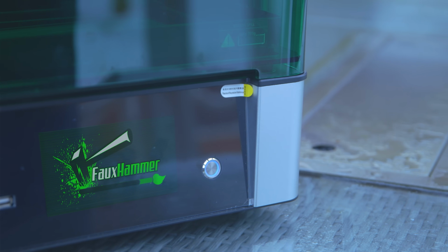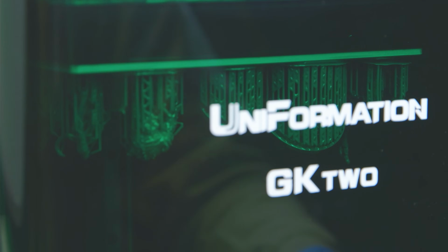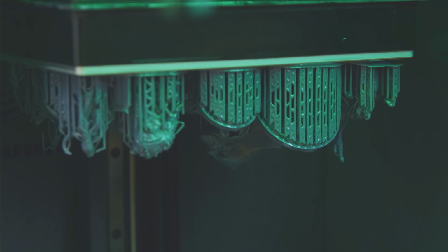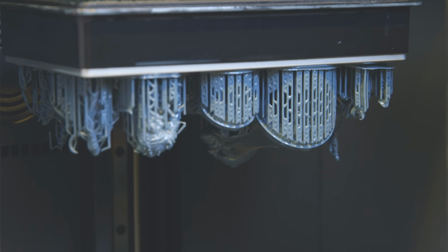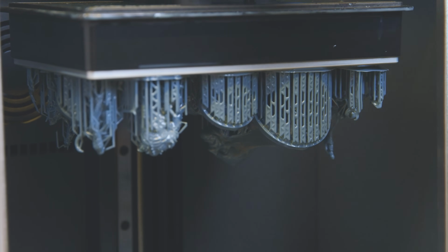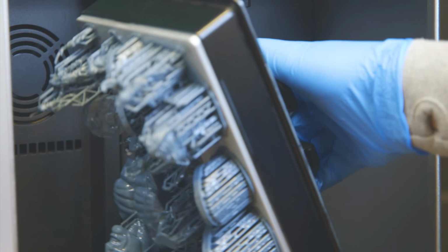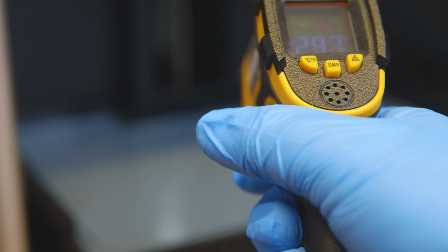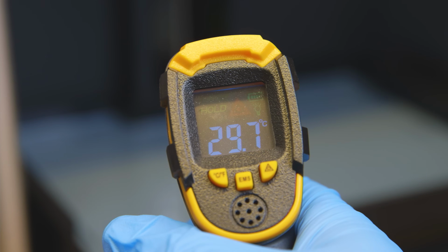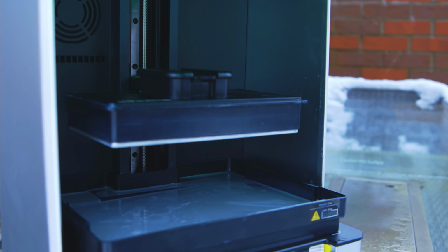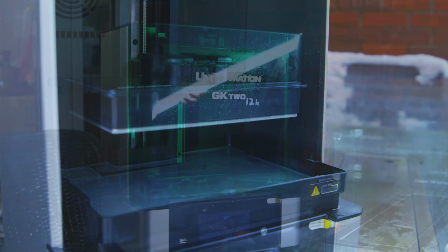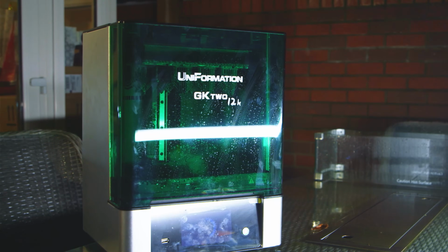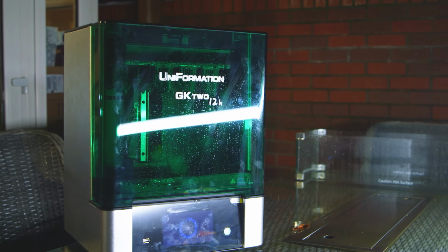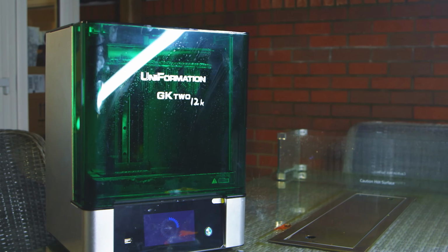I am going to assume a couple of things before we begin. I'm going to assume you've been able to print on your printer. Keep watching, but my earlier video may help you get started. I'm also going to assume that you understand that having consistent resin temperature throughout your print is vitally important. If you dial in your printer during the day and everything looks great, when the temperature drops overnight, your resin becomes less reactive to UV light because it gets colder, and that can lead to fails.